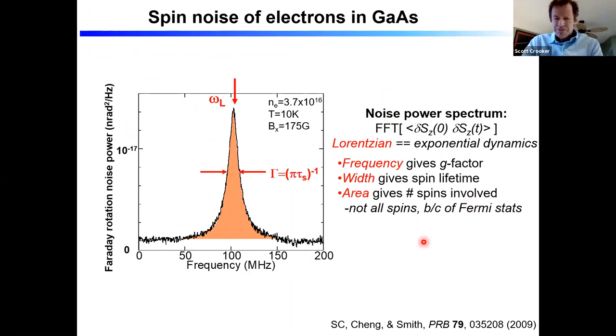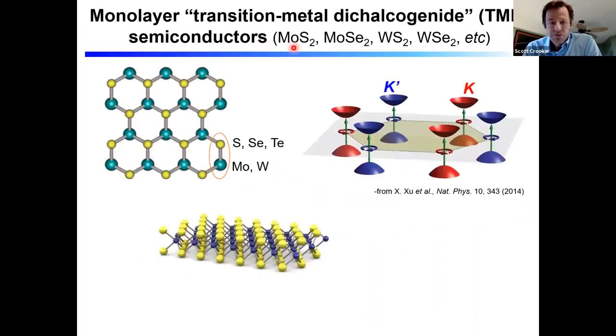So we spent a few years playing with conventional semiconductors and quantum dots and measuring noise signals. Much more recently and more relevantly to this audience, we've since applied this to the new family of monolayer transition metal dichalcogenide semiconductors, which I think many of you have probably heard of. Probably many of you are experts with these materials. So these are things like molybdenum disulfide or tungsten diselenide. And as you may have heard, at least structurally, in their monolayer form, these materials have a lot in common with graphene, at least in the sense that they have a honeycomb lattice.